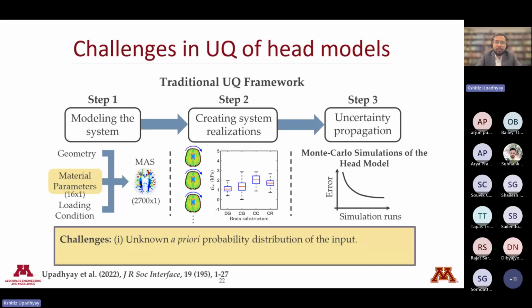Now, this method cannot work for head injury models, or high fidelity modern computational models in general, because, first of all, the probability distribution of the input is unknown. We don't know the probability distribution of the input parameters, or how those 16 parameters vary with respect to each other. Even if we knew it somehow, Monte Carlo simulations usually take thousands or hundreds of thousands of simulations to converge. And these models are very computationally expensive. A 3D model actually used to take 9 days to run on an HPC at Hopkins. Even a 2D model used to take 7 hours on an HPC. So running hundreds of thousands of simulations is not possible.